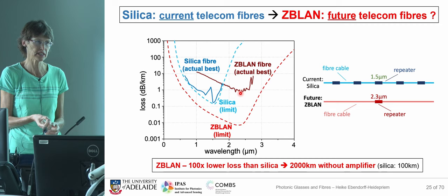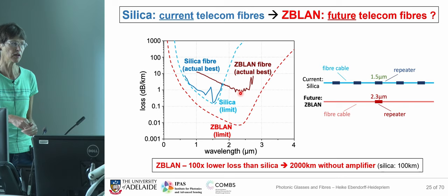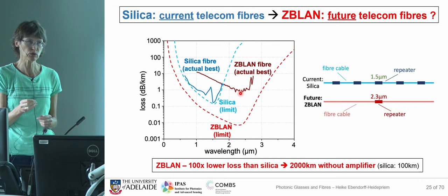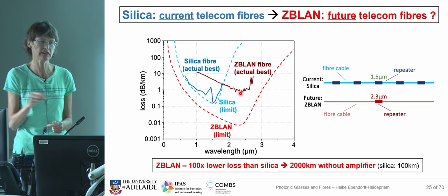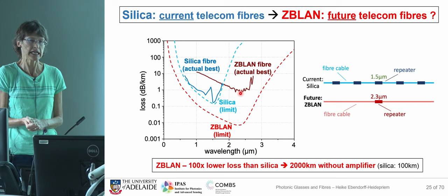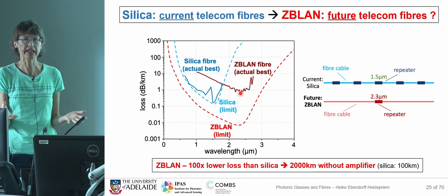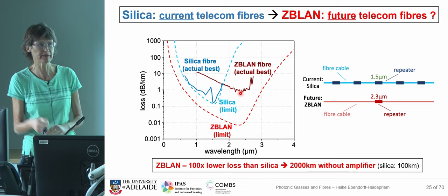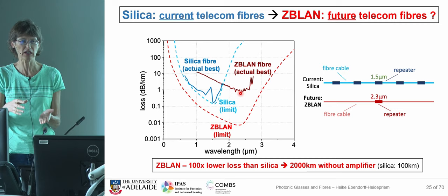The other is the absorption, so the raw material purification. So I started now to hire a postdoc and student in chemistry to purify the raw materials. And purification is one thing. The other thing is we need to achieve purities in the order of sub ppb level, for example, for iron, copper, nickel, and cobalt. And for the preliminary work we have done, we find we are already below the detection limit, but the detection limit is 1 ppm. So we also need to do a lot of work in the trace metal analysis.